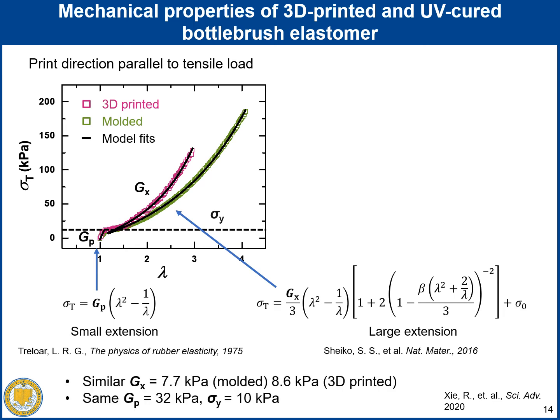As it turns out, the post-yield modulus, G of x, is essentially the same for both 3D printed and molded samples and has a value around 8 kilopascal. And this value is actually about 4 times smaller than that of the pre-yield modulus.